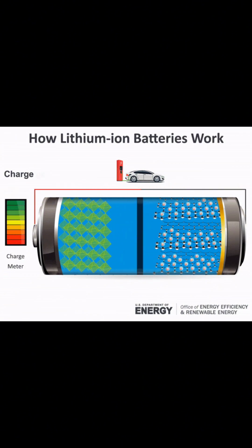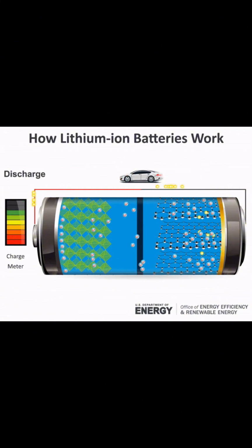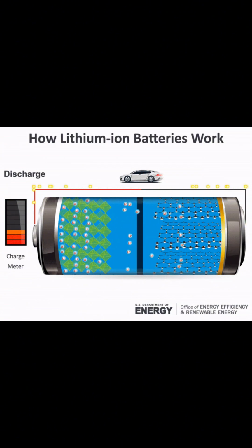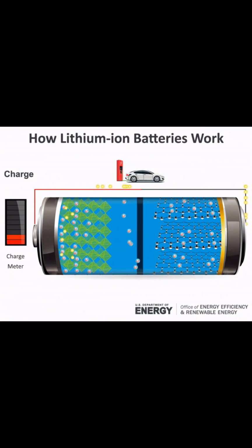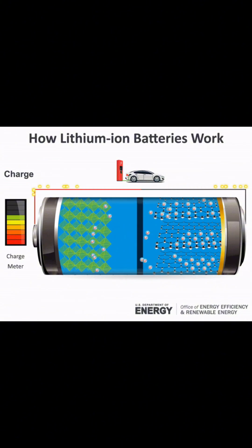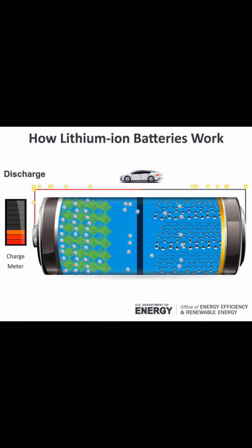Batteries with a lithium iron phosphate positive and graphite negative electrodes have a normal open circuit voltage of 3.2 volts and a typical charging voltage of 3.6 volts. Lithium nickel manganese cobalt (NMC) oxide positive with graphite negative have a 3.7 volt nominal voltage with a 4.2 volt maximum while charging. The charging procedure is performed at constant voltage with current limiting circuitry. Charging is constant current until a voltage of 4.2 volts is reached in the cell, and continuing with a constant voltage applied until the current drops close to zero. Typically, the charging is terminated at 3% of the initial charge current.